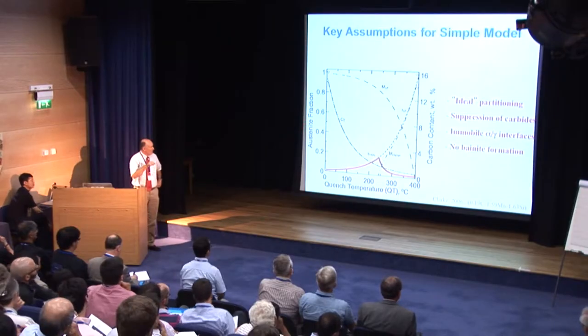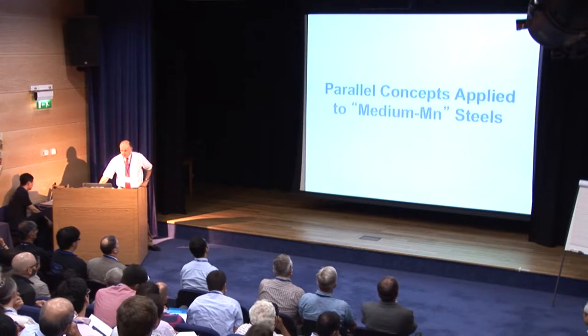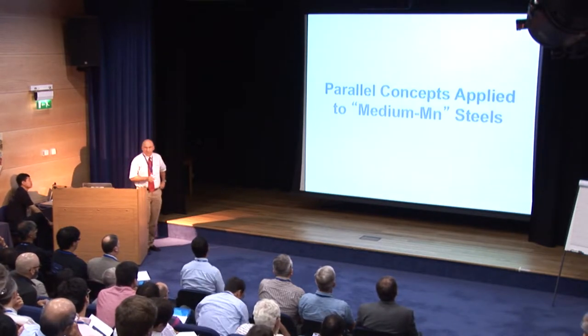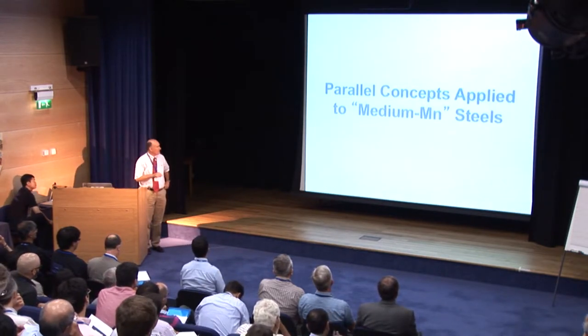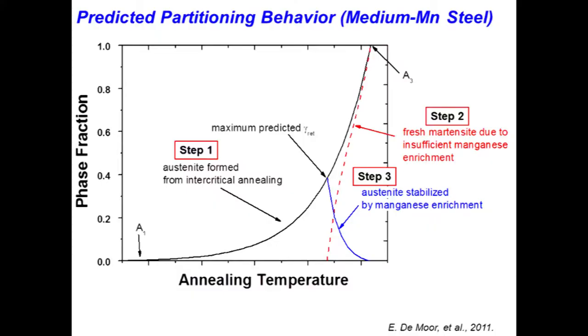Now, this particular model that I described here was actually applied more recently in a completely different class of steels, the so-called medium manganese steels that are very fine-grained intercritically annealed material, so fine ferrite-austenite mixtures where the austenite is really stabilized by high manganese concentrations. And I'll just show you how this diagram was applied in that case.